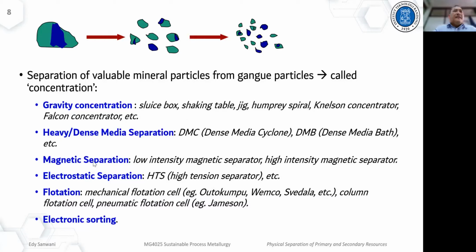Okay. The other technique is magnetic separation, which basically separates the minerals based on their different magnetic characteristics. It can be a low intensity magnetic separator or high intensity magnetic separator. It can be a dry magnetic separator or wet magnetic separator. The other is electrostatic separation. This technique is based on different electrical conductivity. So if, say, the blue particle has good conductivity, whilst the green particle in this illustration is bad in electrical conductivity, then we can apply electrostatic separation. For example, high tension separator.